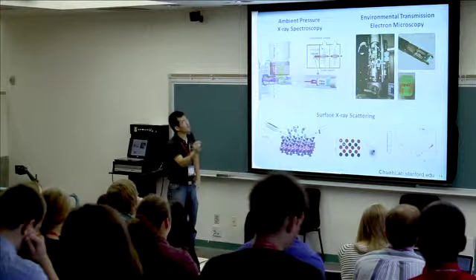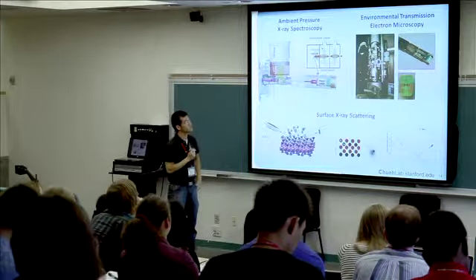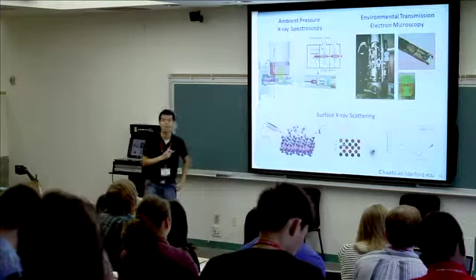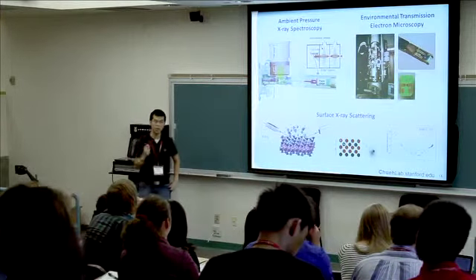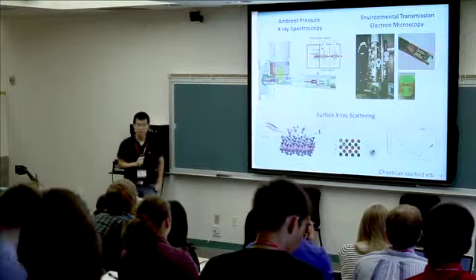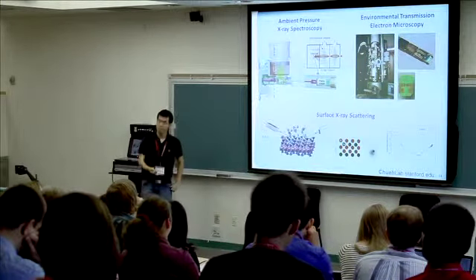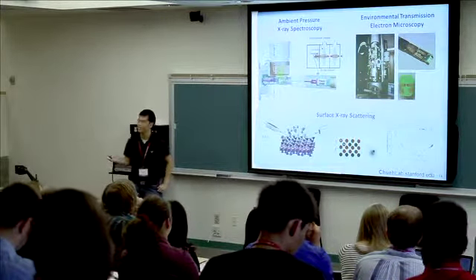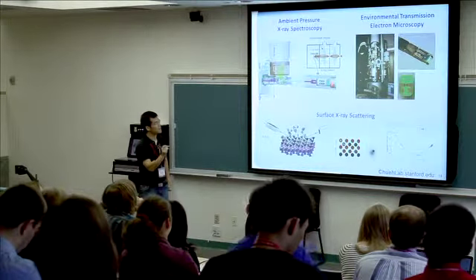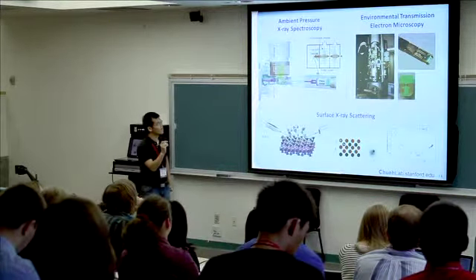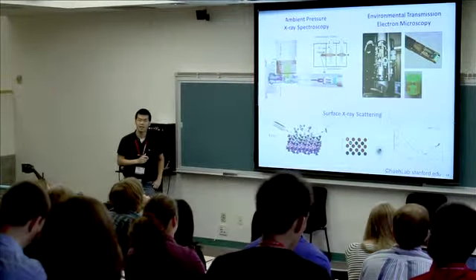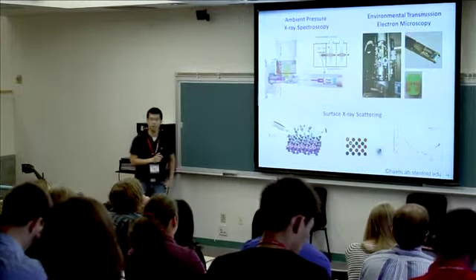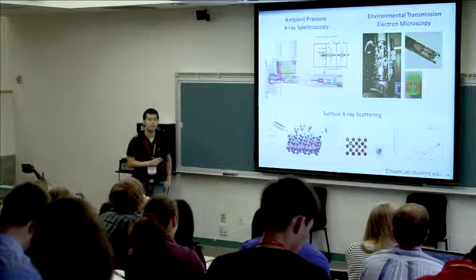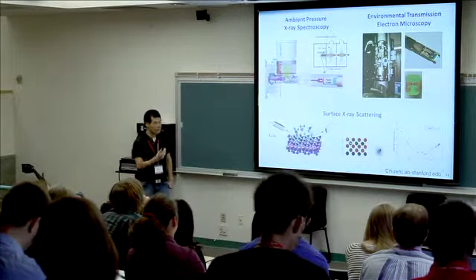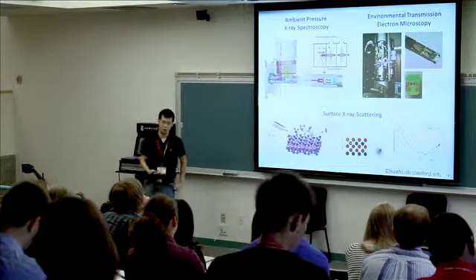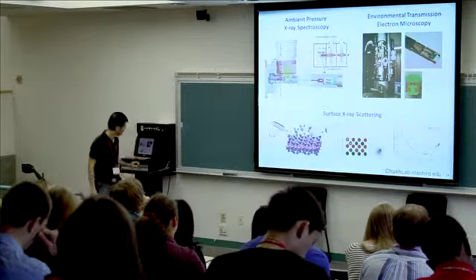Finally, we're also applying a conventional technique, but taking it one step further. Transmission electron microscopy is a great way to get awesome resolution. You can get sub-nanometer resolution, you can see atoms, it's great. But again, most of the time it's done in vacuum, so chemistry can't really take place. But we at Stanford, at the Stanford Nano Center, have a very nice instrument called the environmental TEM. This allows us to run reactions on the order of 20 millibar. So again, we can put in all the gases and watch with atomic resolution what is happening to the materials.